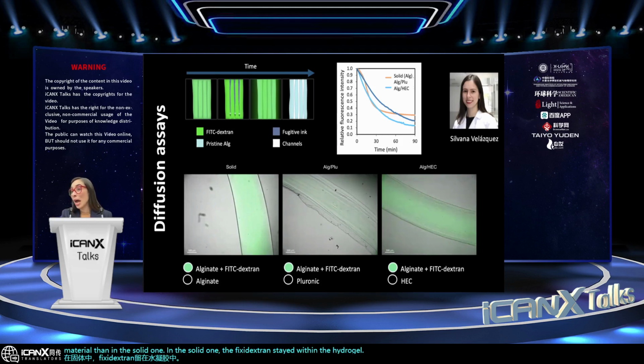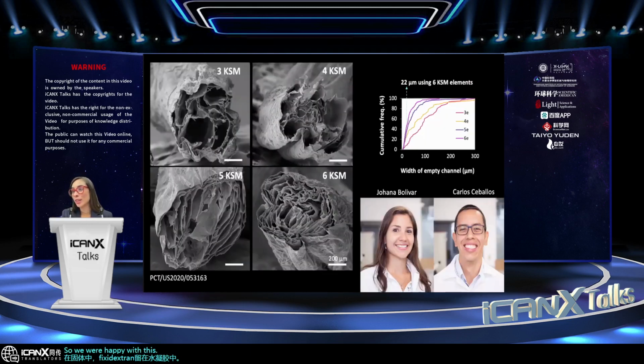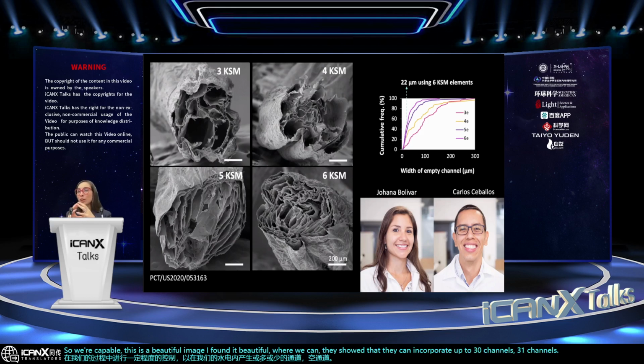So we were happy with this, and Carlos and Joanna, they are very ambitious, and they want to push the technology forward, and they were capable of having some degree of control in our process to produce more or fewer empty channels within our hydrogels. So we were capable, this is a beautiful image, I found it beautiful, where they showed that they can incorporate up to 31 channels inside a 1 millimeter filament of hydrogel.